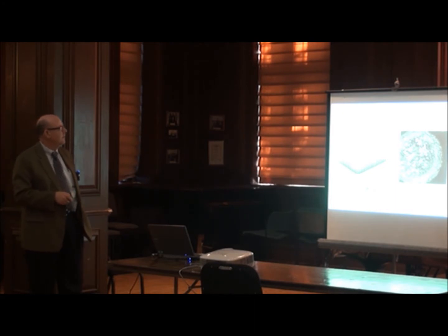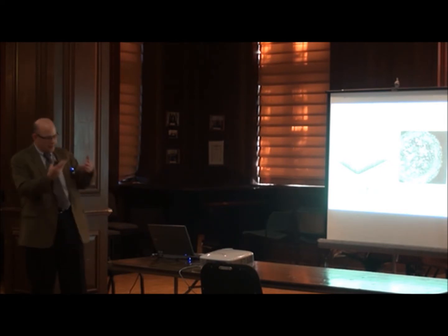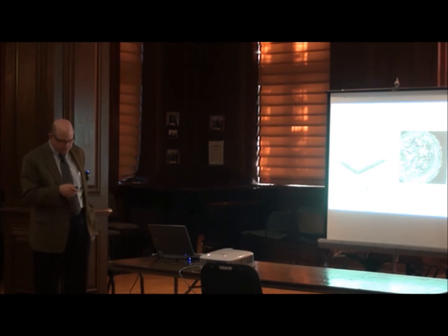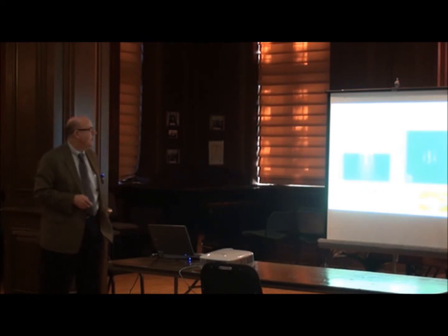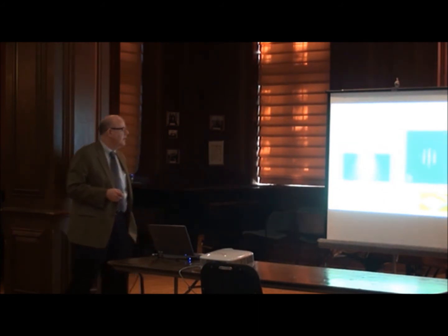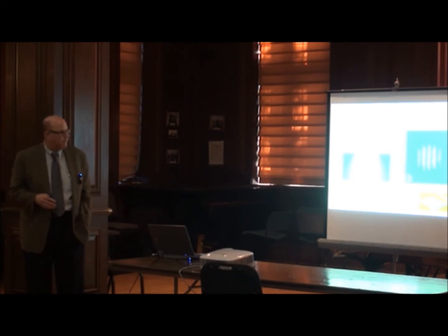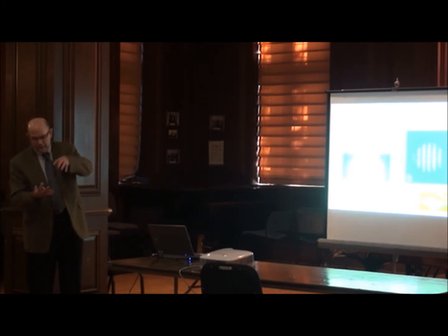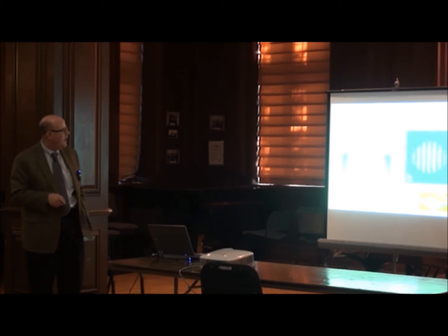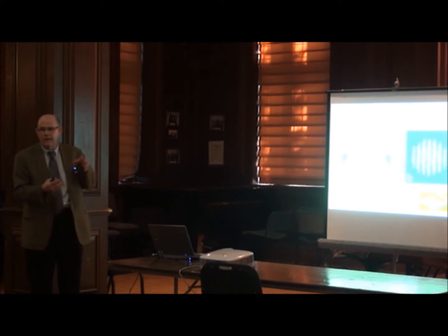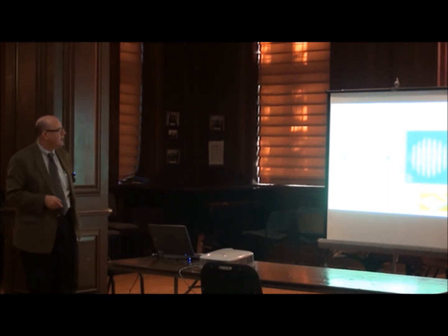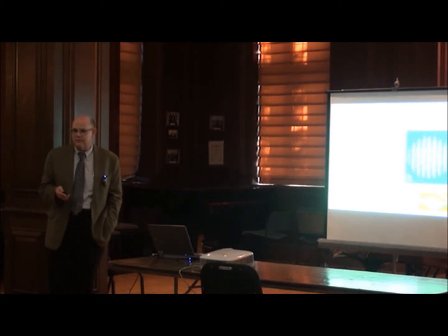But this is some of the work he did a few years back with particularly gear teeth. And what's being plotted here is basically if the two gear teeth come together under a certain load, what the area of contact is, and those are those white spots here. Okay. Now I can go a step further in his computer modeling. This is a real simple example of a movie he puts together, taking a curved surface and bringing it into a flat surface. And as I bring it in under load, it's basically showing the real area of contact growing and how it would grow for this particular texture. This calculation also assumes what can go on subsurface. It calculates the stresses and so forth.